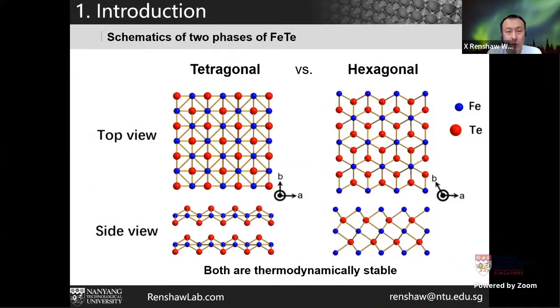Now, talking about these two structural phases, for the tetragonal phase, at least here, the top view you can see is a tetragonal lattice, and the hexagonal is obviously just a hexagonal lattice. I listed the top view and also the side view for you to have a better understanding. And both phases are thermodynamically stable, meaning that we are able to fabricate them and the structure won't collapse.